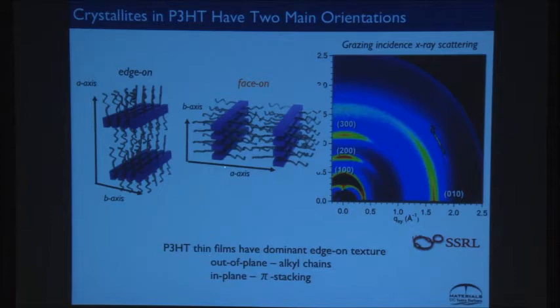When I look at a polymer structure, they tend to pack like this, where this is a backbone. And these are the side chains that make it soluble, so I could dissolve that material. I could imagine I could have crystallites that are oriented with the A-axis up, or I could have them A-axis in plane. It's very hard to get the other axis, C-axis, up because of the chain length. So typically you get one of these two structures.